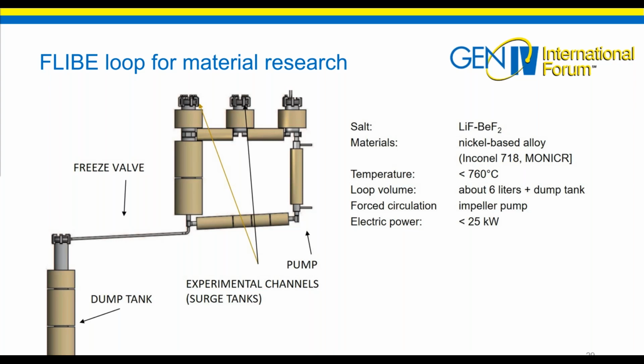In 2017, we built our FLiBe loop, which should help us to do corrosion tests of selected structural materials, samples not only of MONICR, but also other nickel alloys and other materials. And for your information, the loop is made from Inconel 718 alloy, and it also contains the freeze valve and a relatively primitive pump. The loop has about 6 liters plus the volume of the dump tank, and it is heated by electric power.